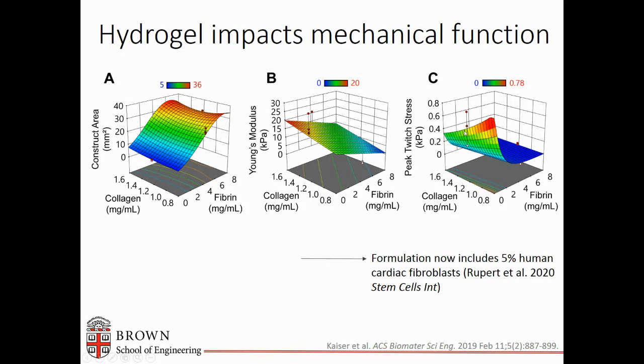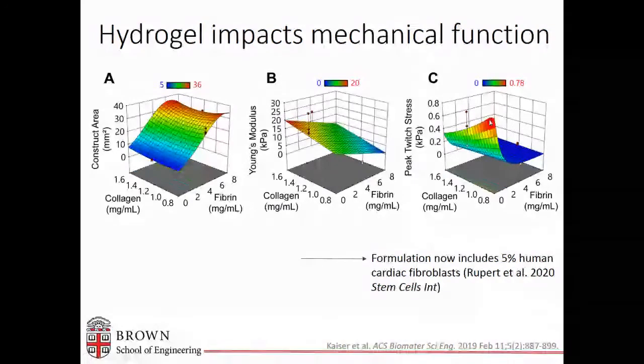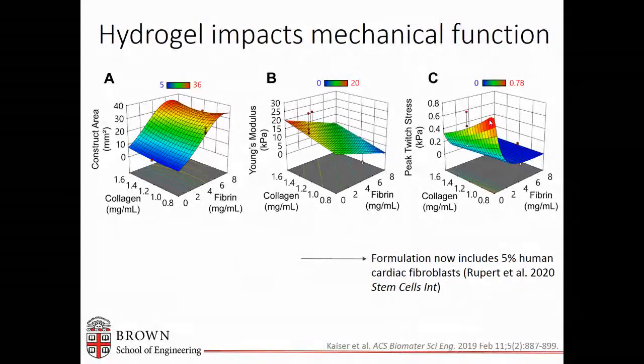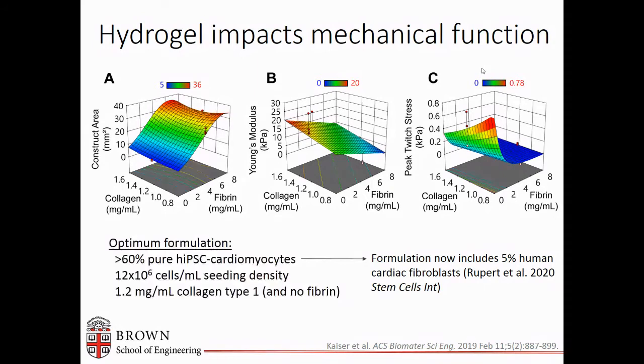Again, these are the data points in the middle at 1.2 mg per mL collagen that we measured. And we actually created this group. What we found was that the tension created by the cardiomyocytes actually caused necking and breakage in half of the engineered tissues. So while the model predicted that to be a high point, it was not actually feasible. We determined from this study that we needed greater than 60% pure cardiomyocytes with our given seeding density and 1.2 mg per mL collagen. And our formulation now includes 5% cardiac fibroblasts, which is a paper recently published just last year.